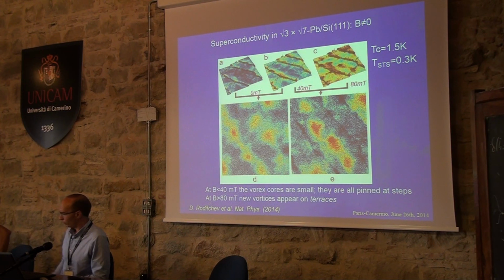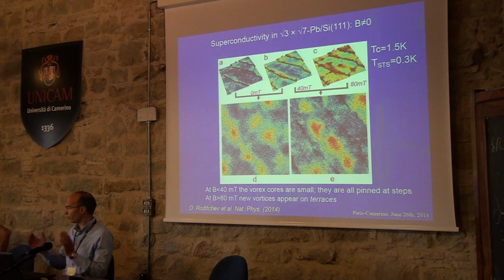And if you raise the magnetic field and do a difference map between 80 millitesla and 40 millitesla, you get the right map, and you see that additional vortices are all sitting on terraces, and all these vortices are Abrikosov vortices. So this system is a very interesting playground for multi-component superconductivity, Josephson networks, and all these new kinds of vortices you can get. Thank you very much for your attention.